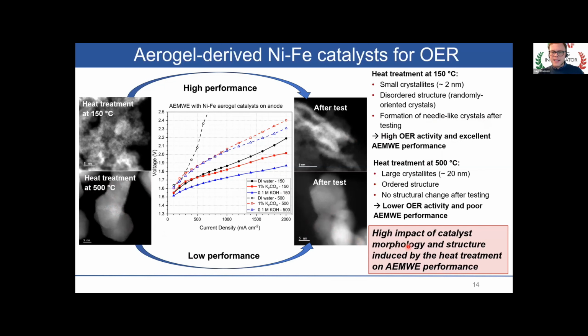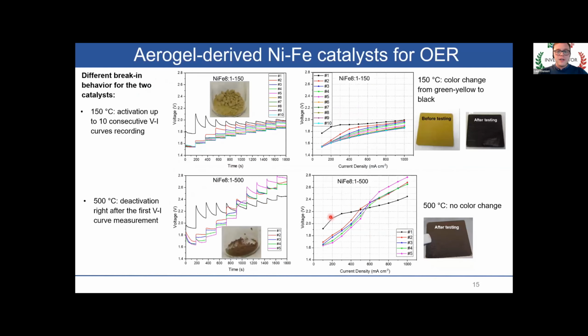And so we have elucidated how the catalyst morphology and structure induced by heat treatment, for example, can improve the performance on application of this catalyst in a real water electrolyzer device. We also investigated the break-in of these materials in an electrode, showing that the good performing catalyst actually shows a continuous activation over up to 10 polarization curve measurements, showing also a color change from greenish yellowish to black, while the low performing catalyst started to degrade right after the first polarization curve measurement and did not show the same color change.